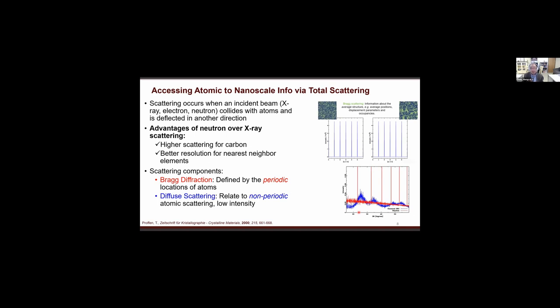So, assessing the atomic to nanoscale information through total scattering. First, we need to look at the scattering that we're familiar with, which is Bragg scattering. Here we see these very sharp peaks, which give information about the average structure. This overall lattice diffracts.